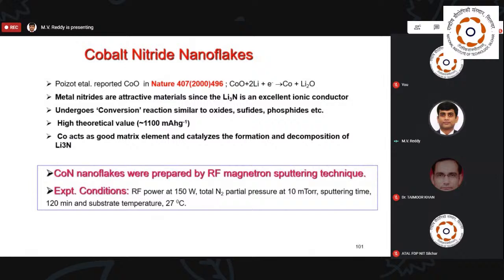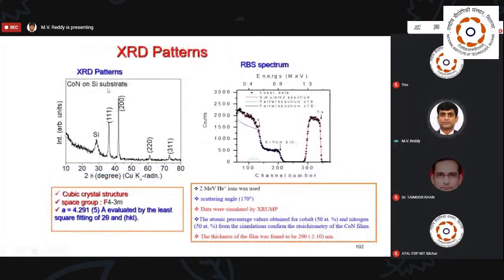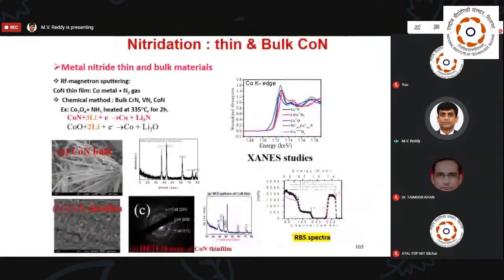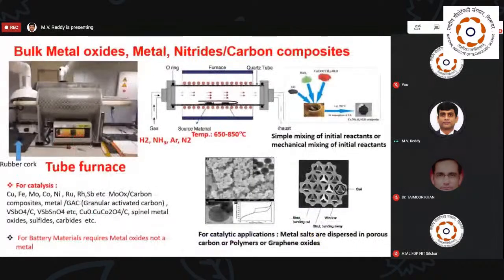Also, we checked some cobalt nitride made with simple sputtering of cobalt. I told you, with cobalt metal and nitrogen gas, we can get, either with X-ray, the expected cobalt nitride films, and with respect to the thin film, using the RBS approach, we can do this. Since my time is short, we can also do some bulk materials, etc.